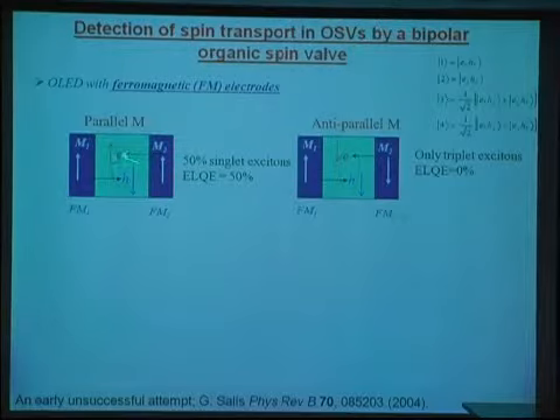So in this configuration, we inject electrons with spin up, the same as the magnetization here, but the hole with spin down. So based on the possibility of the spin pair singlet and triplet configurations here, you can see that we only form state number 3 and number 4, which means we have 50% singlet states in this configuration. And the quantum efficiency in this configuration is 50% because only singlets emit light. But in the other situation, you can see that the spins of electrons and holes are parallel. So they form only triplet states, and in principle there is no light in this configuration.